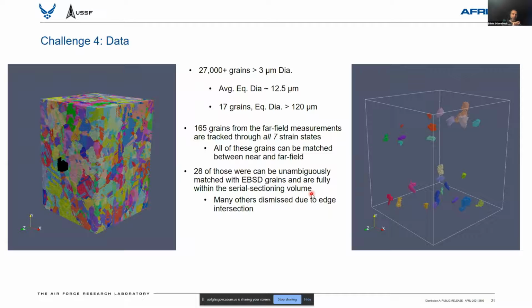Of that large collection of grains, we could clearly track 165 of them through all of the loading states, all 7 strain states. And of those grains, just under 30, 28, I think, could easily and very clearly be linked back to the higher fidelity description of the microstructure that you see on the left-hand side here. So these 28 grains formed the basis of the challenge. The full microstructure was provided as part of the calibration data or input data. The stress-strain curve for the whole specimen was provided again as the input data, and then the question was basically what is the elastic strain in any of these individual grains at the various different loading states. So the idea here is to provide some data for characterizing, for instance, crystal plasticity finite element type models of these very local evolution of mechanical properties.